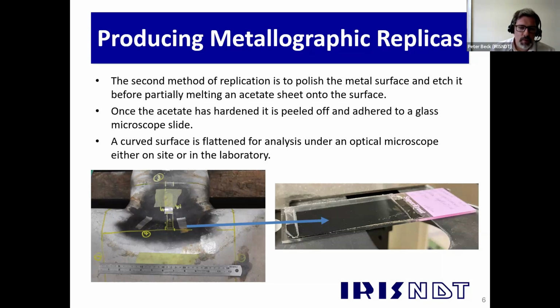One thing to say is that we typically do replication for creep assessments. With that, we would look to replicate both toes of a weld. You can see in this image, we've replicated 3 positions: 1 on one toe and then 2 positions on the other. That's because we've got a crack there that we actually replicated the crack tips. But essentially we want to capture both the weld metal and the parent metal each side of the weld. So we typically would have about 1/3 weld metal and 2/3 parent material in a replica, and that's why we need to take 2 generally, because the welds are just too large to get into one replica.